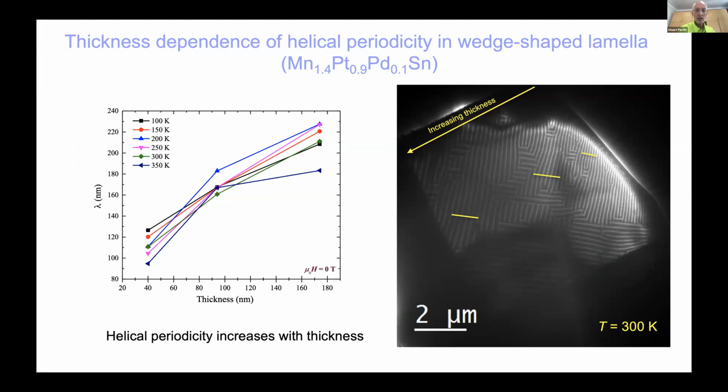And what we found, interestingly, even for this limited thickness range, here from 40 to 180 nanometers from the Lorentz microscopy, we're looking here not at the antiskyrmions, we're looking at the helical phase in the black and white stripes, which you can see on the right-hand side. They're oriented largely in one of two directions. These directions are those directions in which the wall type of the antiskyrmion is a Bloch wall. This is the lowest energy wall when you take into account dipole fields, dipole energies.